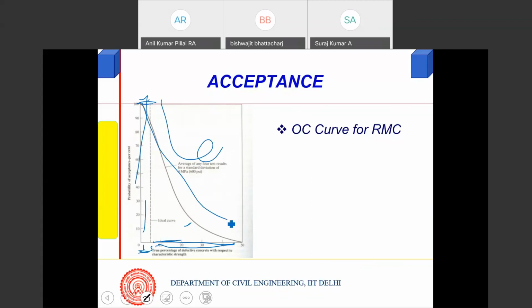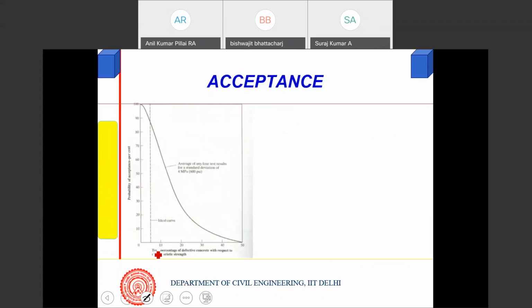But actually it is found something like this. Let me repeat it. If the defective is less than 5%, it should be 100% accepted. If defective is more than 5%, 100% rejected. That actually should be the ideal condition. But it can so happen that you have produced less than 5% defective, but there's still a probability of rejection, because this is the probability of rejection and this is the probability of acceptance. Below this is the probability of acceptance, because the actual operating curve is something like this.